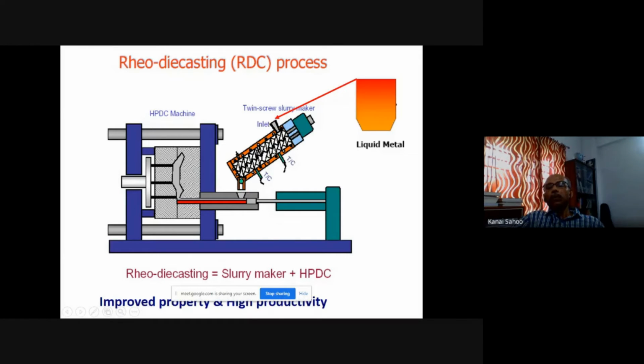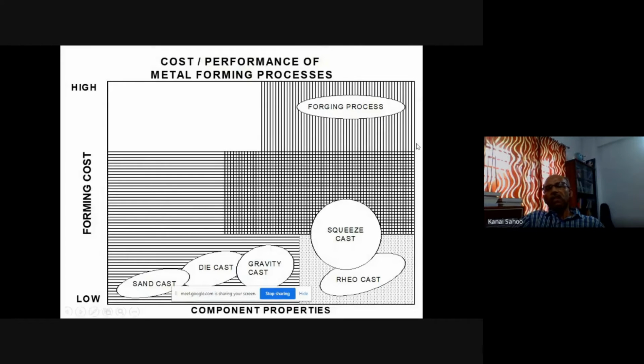So that is why people have developed rheo die casting. That means you do the rheocasting over here. Professor Fan at Brunel University basically developed this technology. Some of the industry are now adopting this. So here you do the rheocasting, and then with the twin screw mechanism, all the slurry content you just remove and put in the high pressure die casting. So this gives highly improved properties with high productivity. This is a newer casting technology. Hopefully it will come in a big way in coming days. If you compare the cost performance with forging process, squeeze casting, all these processes, the rheocasting forming cost is low and component property is very high. But still, a lot of the rheocast processing parameters need to be improved.